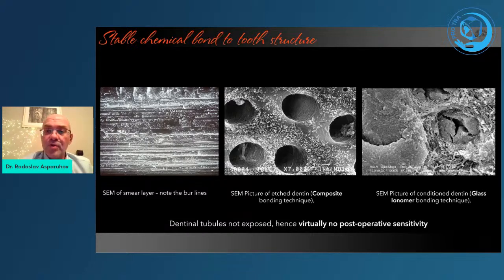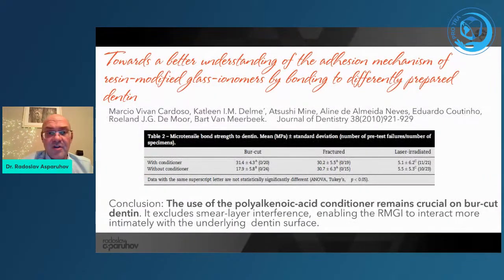So that means that we do not open the dentinal tubules, therefore we do not experience postoperative sensitivity. But you can see on the picture on the left that the grooves left from the burrs are actually covering the whole dentinal surface and create a very, very thick smear layer. So that's why it is always recommended, whenever we have burr-cut dentin, to use dentin conditioner or cavity conditioner to clean this surface.